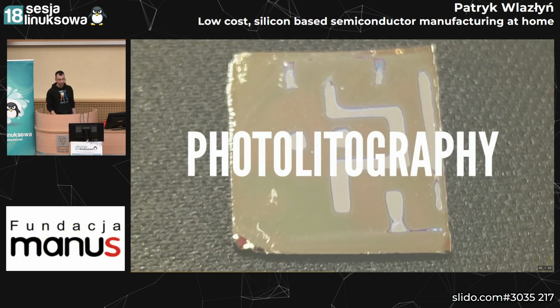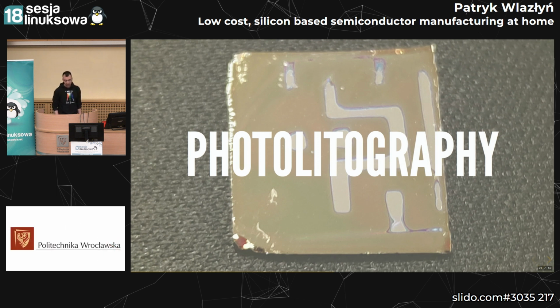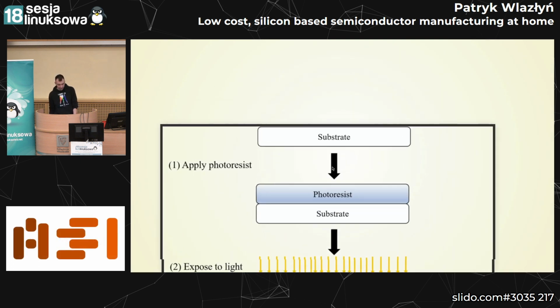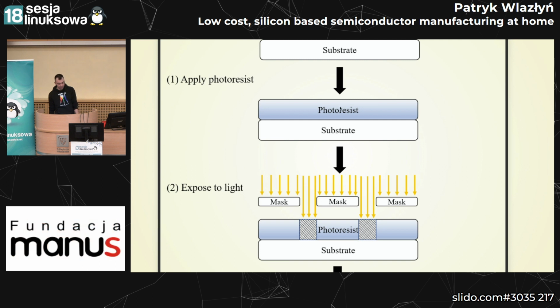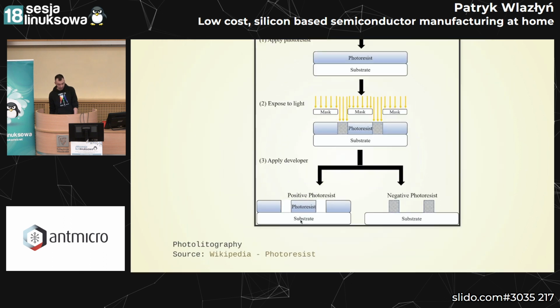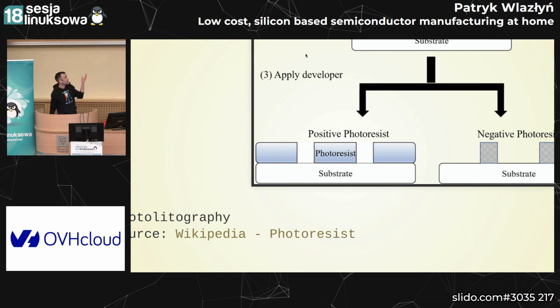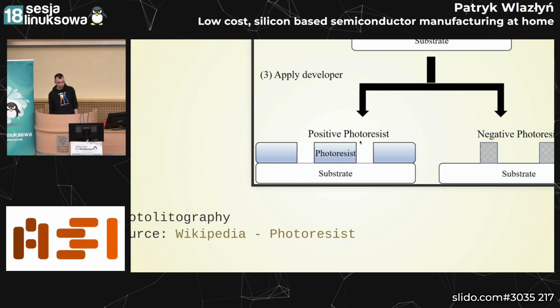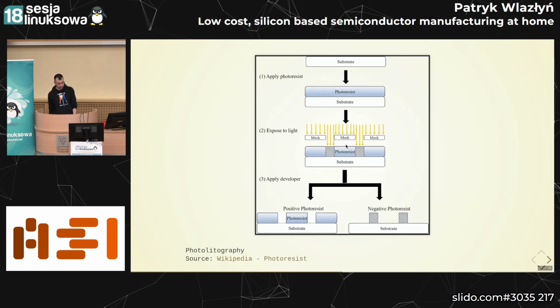Okay, and now we go into the photolithography process, which literally means drawing with light. It's a way to remove a photoresist only in certain places. We shine UV light only in certain places, creating the circuitry that we want to embed into the silicon wafer. It works like this. We have a substrate, in our case a silicon wafer, and we spin coat a photoresist on top of it. Later we apply UV light and use a mask to block UV in certain places. In the places that were exposed to UV, we apply a developer, which is a different liquid, and it removes the photoresist only from the places that we were shining the light through.